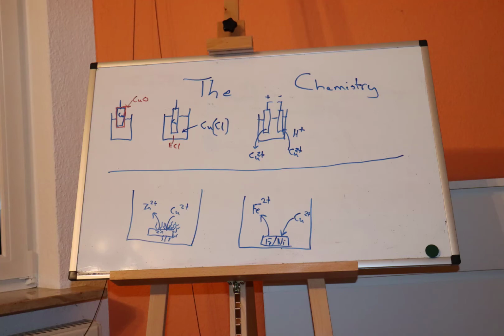You can see that this process is comparatively simple to do in practice, but there are some complexities in what actually happens. Looking up on this whiteboard, we can see in the normal case, copper is covered with a copper oxide layer, and that makes it safe even if we leave it in water for quite a long time. If we put it into acetic acid or vinegar with some salt in it, it behaves very much like hydrochloric acid, and the copper oxide dissolves as copper chloride, but then it stops doing anything because there's nothing to oxidize it to take the electrons away from the copper.